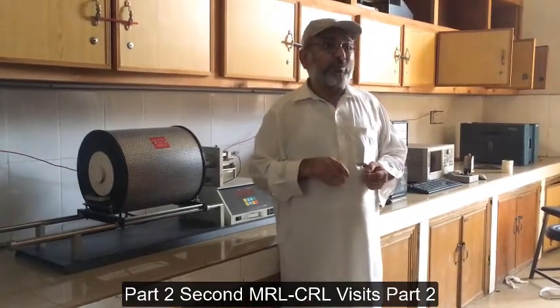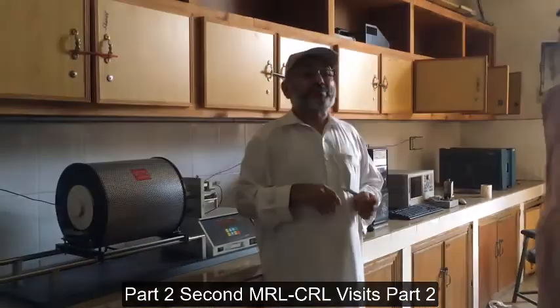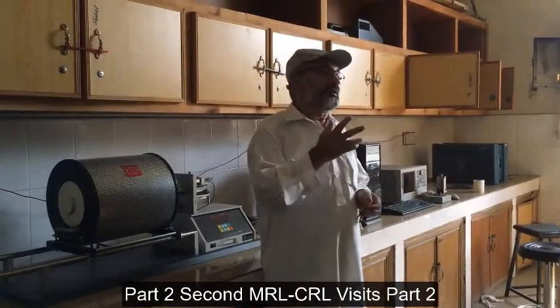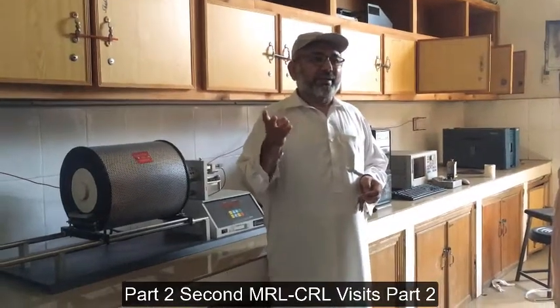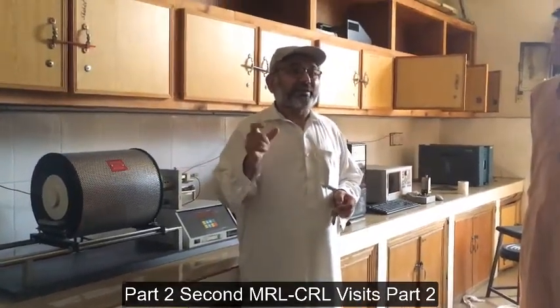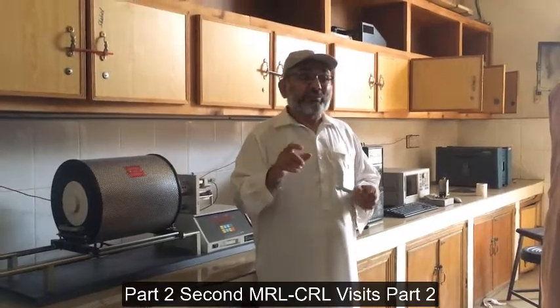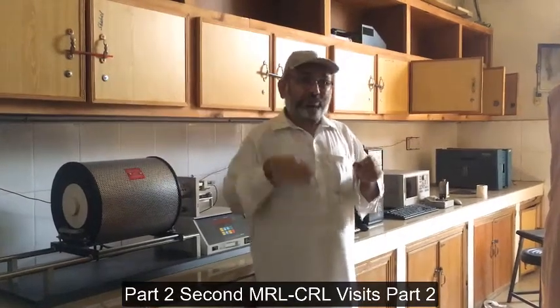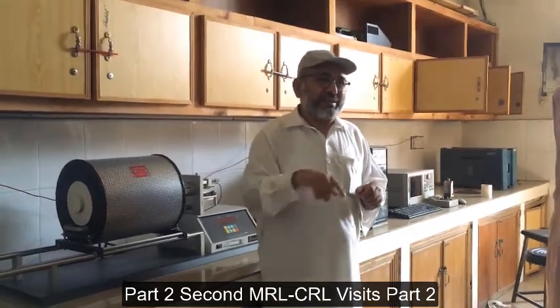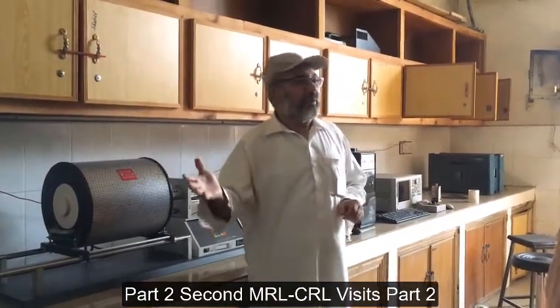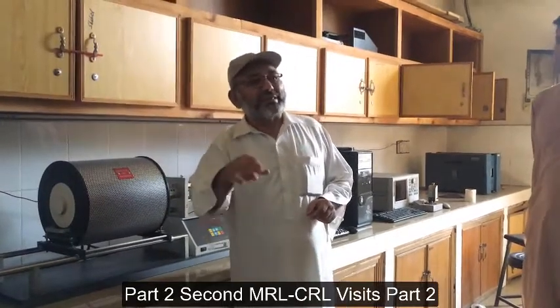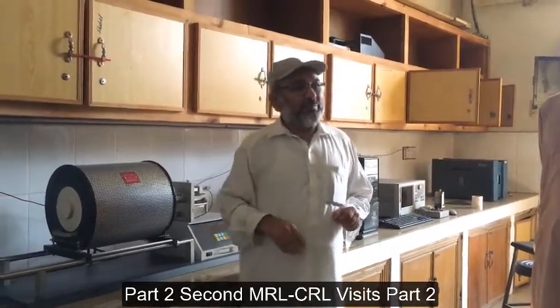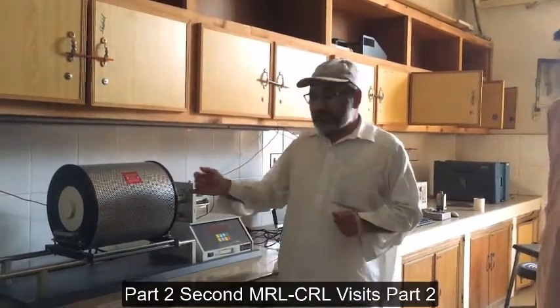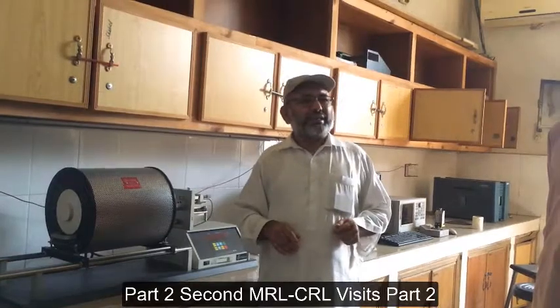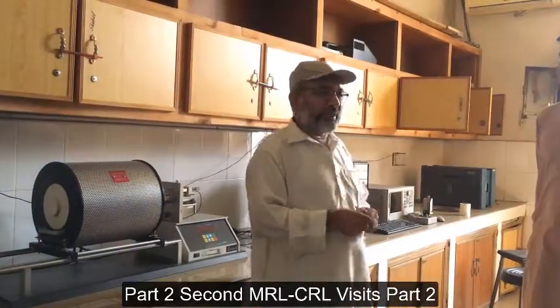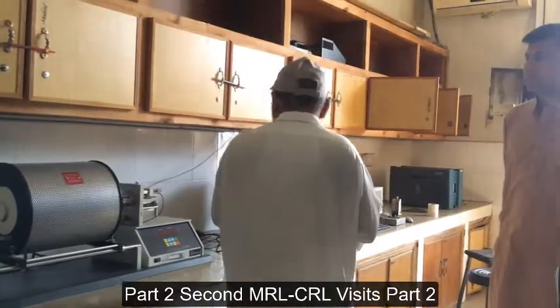In particular, I have more thermal expansion coefficient mismatch in bone china, because you have two phases mainly there, hydroxyapatite and anorthite, and their thermal expansion mismatches a lot. When you make a bone china material and put it in the microscope, you will see many cracks around it, just like when you have stagnant water and it dries up and cracks appear there. So it is almost the same type of phenomenon. It gives you the glass transition temperature as well. It gives you the yield point of the material as well, from where the plastic deformation begins.